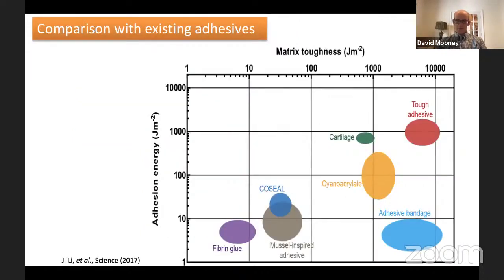Now, Jane Yu was able to demonstrate that this material has performance that actually is better than any of the materials that were out there in the field at that point in time, including the fibrin-based materials, the PEG-based materials, the cyanoacrylates, and really provided a quite appealing set of properties that potentially could be useful in many contexts in medicine.